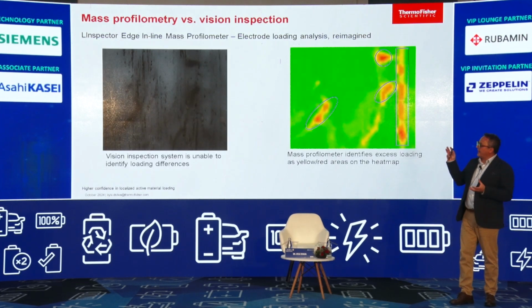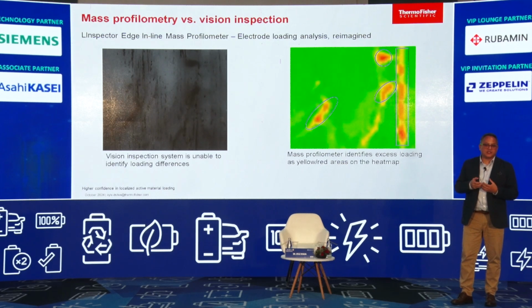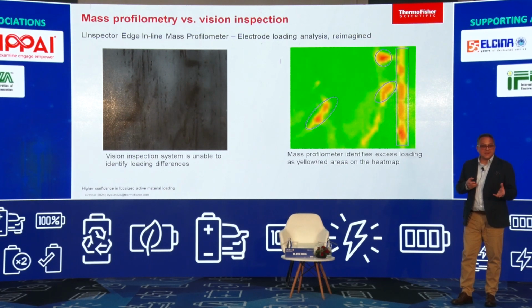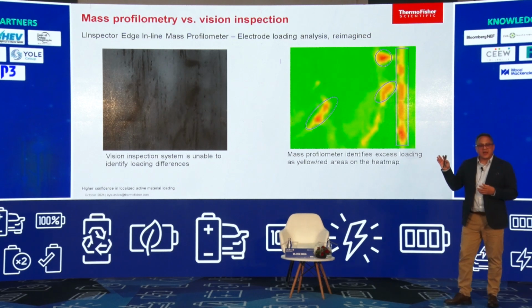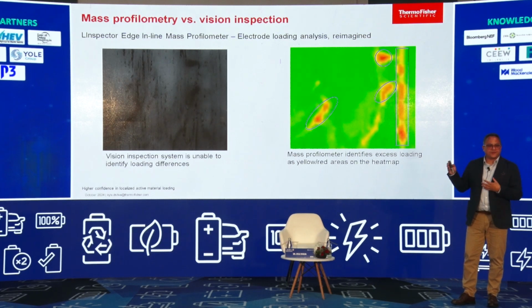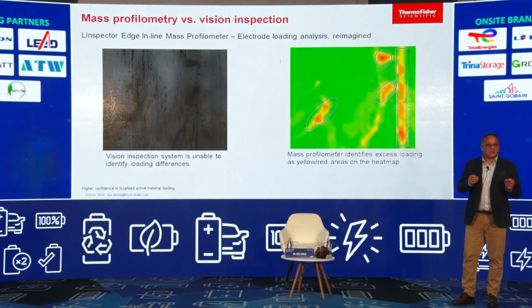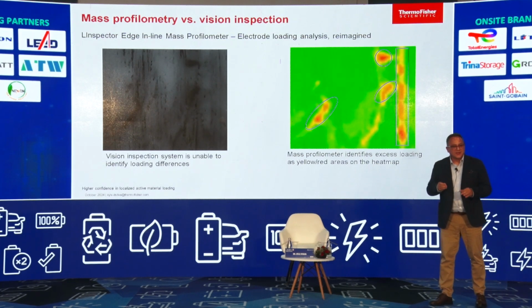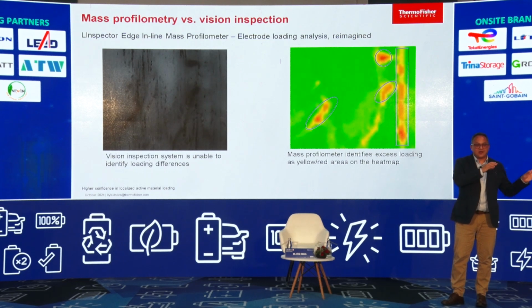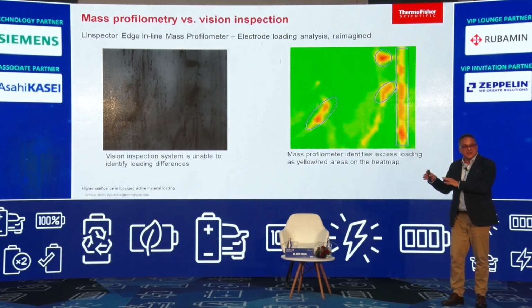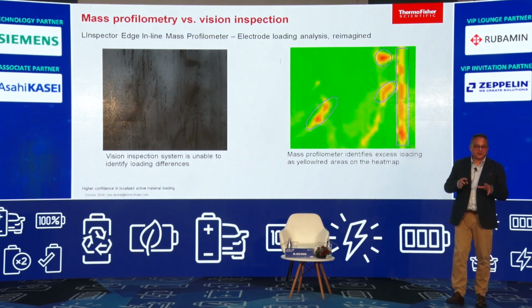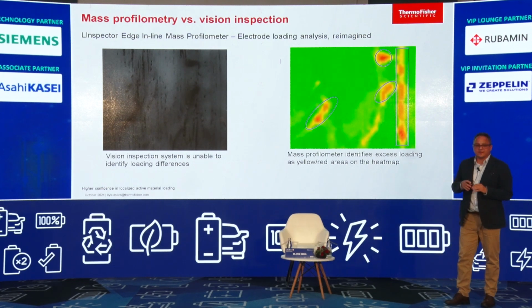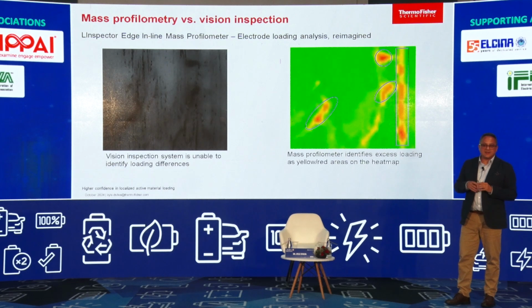So here you can see on the left-hand side a very high definition visual image of a coated patch. And you can see some dark patches, some light patches, but you can't tell whether the material there is thick or thin. And the important part about electrode coating is it's a little bit like Goldilocks' porridge. Too thin is not adequate. Too thick is dangerous. It has to be coated just right to remove the possibilities of failures of the battery at a later stage.